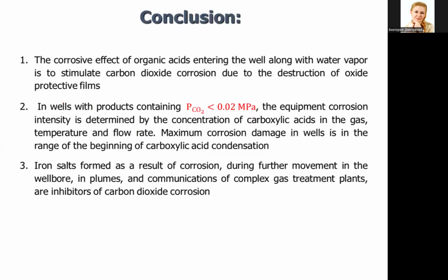So, in conclusion, firstly, the corrosive effect of organic acids entering the well along with water vapor is to stimulate carbon dioxide corrosion due to the destruction of oxide protective films. Secondly, the equipment corrosion intensity is determined by the concentration of carboxylic acid in the gas, temperature, and flow rate. Maximum corrosion damage in wells is in the range of the beginning of carboxylic acid condensation. And thirdly, iron salts formed as a result of corrosion during further movement in the wellbore, in flowlines, and in communications of complex gas treatment plants are inhibitors of carbon dioxide corrosion.